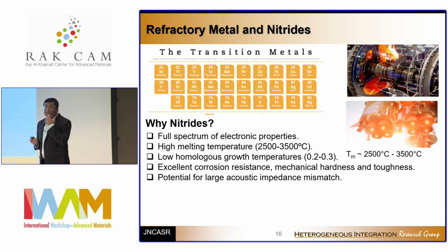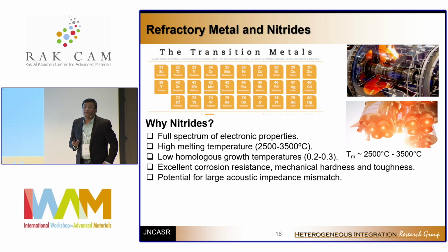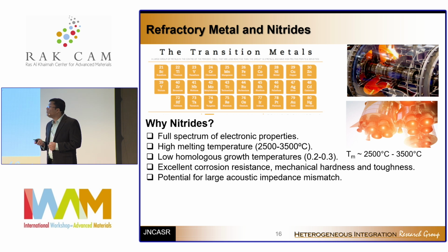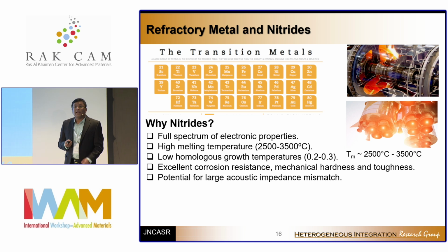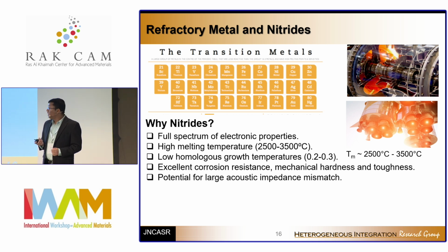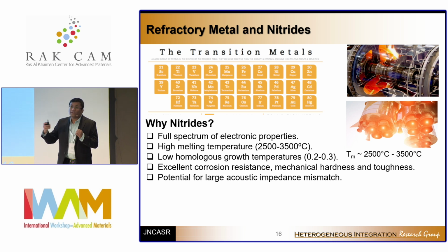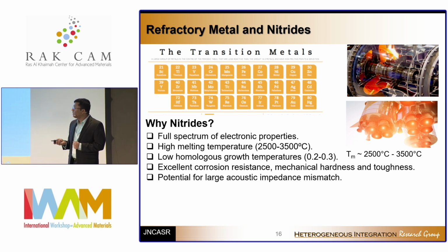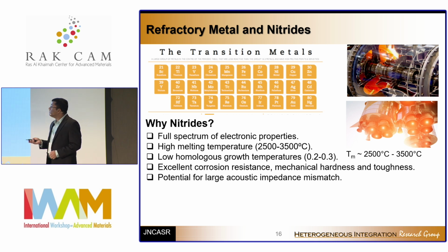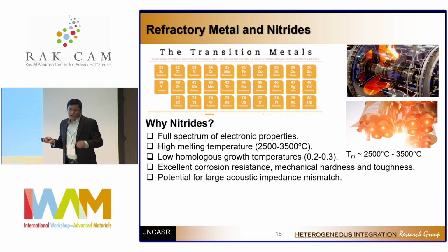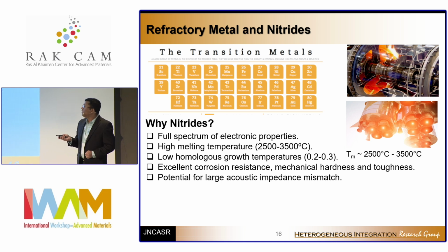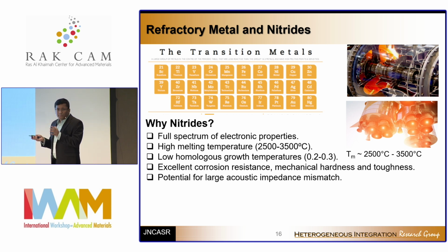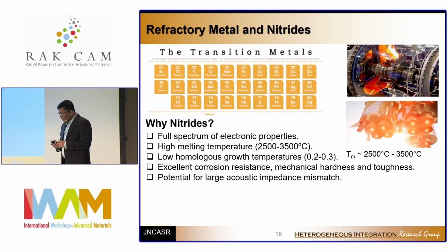Now, why nitrides? Because nitrides actually give you a full spectrum of electronic properties. I shall show you. In the nitrides, there are very good metals like titanium nitride. Nitrides have these III-V semiconductors, which are world famous. And nitrides also have dielectrics, which are aluminum nitride or boron nitride. So it offers you a tremendous spectral variation of different properties in nitrides. Nitrides are known to be corrosion resistant, mechanically tough and hard. And they also offer potential acoustic impedance mismatch, which I'll come back to later, and growth conditions which are pretty reasonable to achieve in the lab.